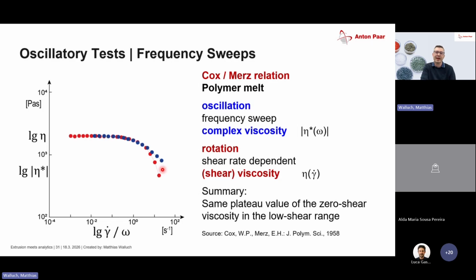This is due to the fact that when we do a shear rheological test on an elastic material, the sample just leaves the gap between the upper and the lower measuring system. So we lose material, and therefore the torque that we measure goes down, and therefore the viscosity looks like it goes down, which is not the case. So in this case, the blue data would give you the correct results. And additionally, we get the information about G prime and G double prime.